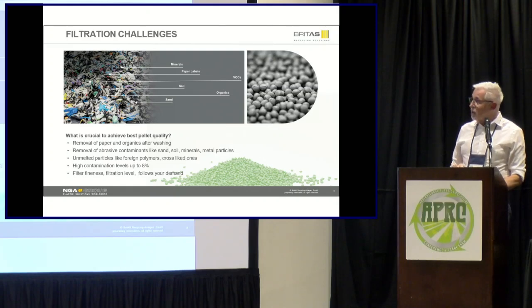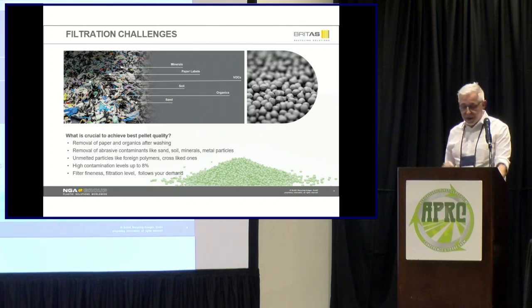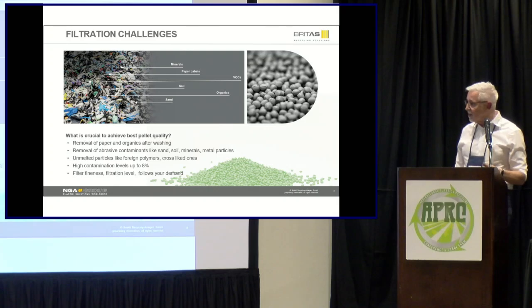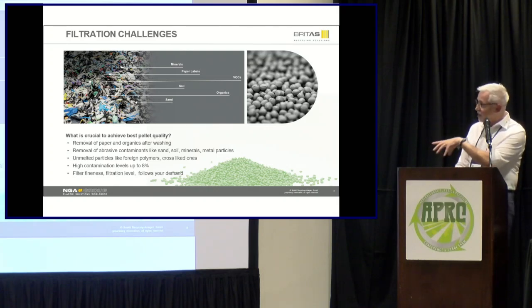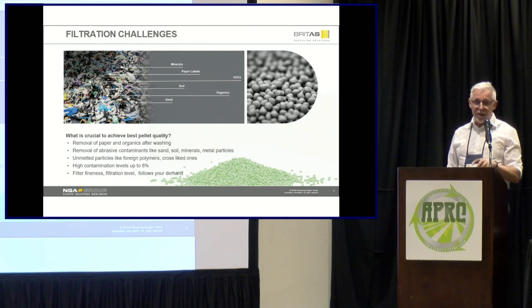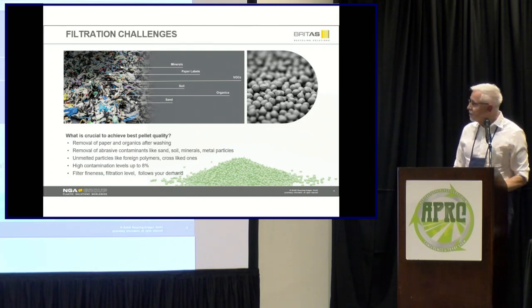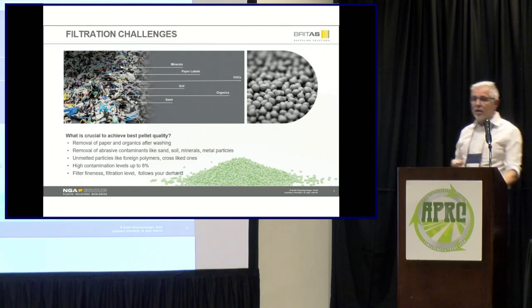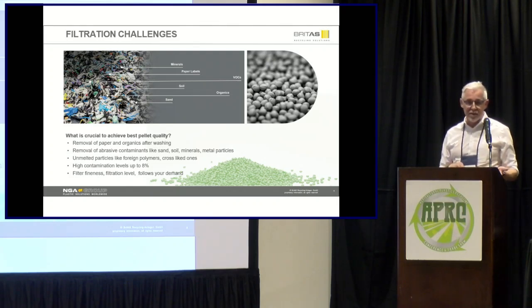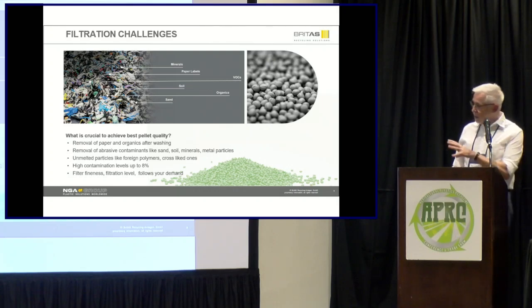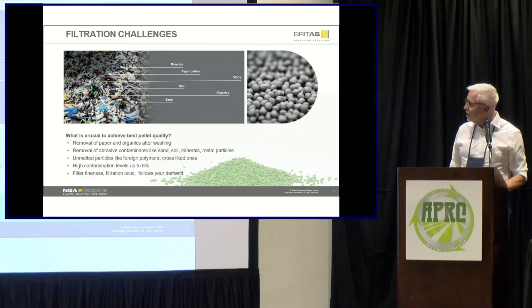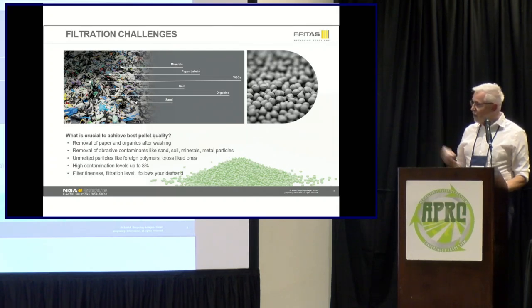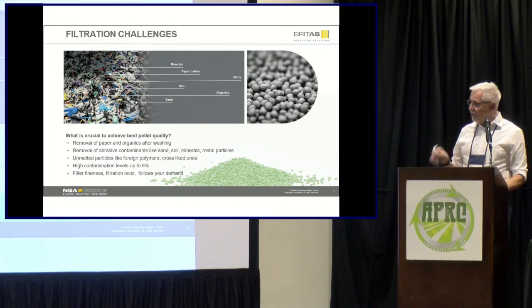So, in particular, for melt filtration, we have to have the possibility to remove paper, organic ones. We have to remove the abrasive contaminants like sandstones, glass, metal parts, small metal parts, and so on, as well as unmelted foreign polymers or cross-linked ones. Even these things have an impact on the pellet quality. And we have to bear in mind that even if we have pretty good washing or drying, or not so good washing, drying, you find contamination levels up to 8%.